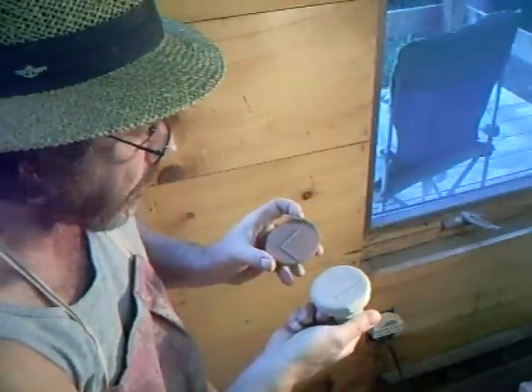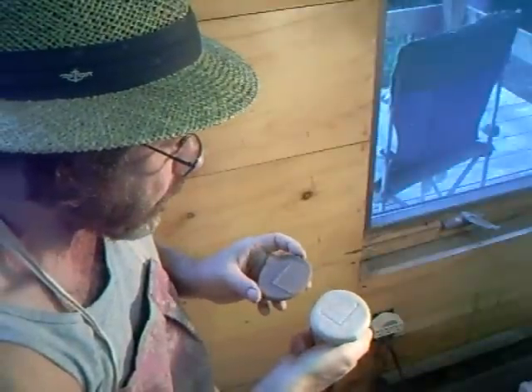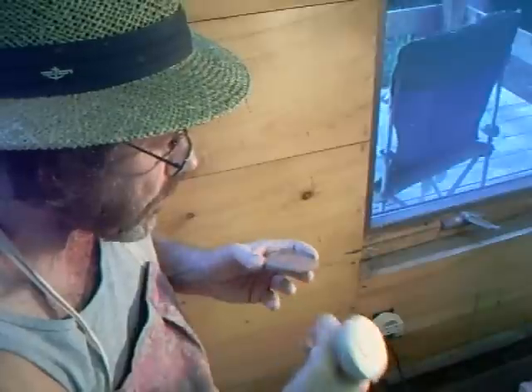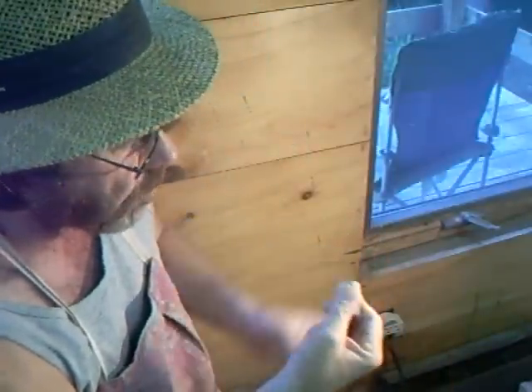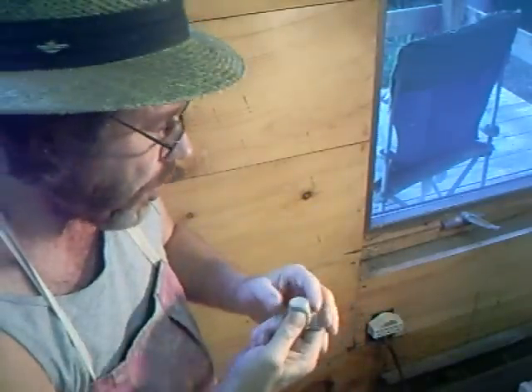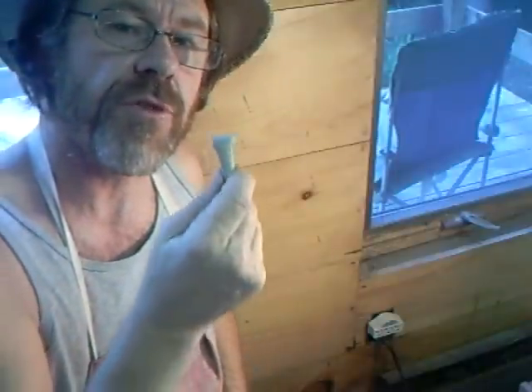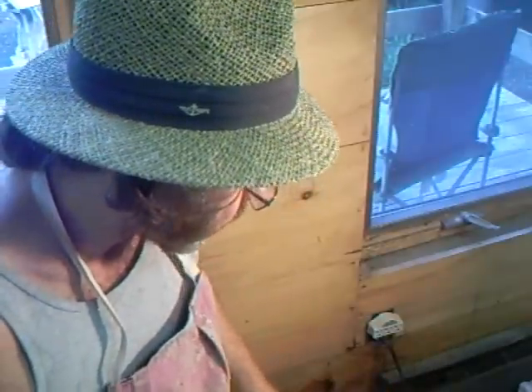And as I say, if you use plaster of Paris, that's very good, and probably better than this. You just have to form it into something. You know, these are useful little things. I can just hold them like that between my finger and thumb to impress on the bottom of a pot. Don't forget, we need to bisque fire these. All right, they need to be bisque fired, not a hard bisque either, so they're still absorbent. That's actually quite important if you're using the clay. If it's plaster, you don't need to fire it, of course.